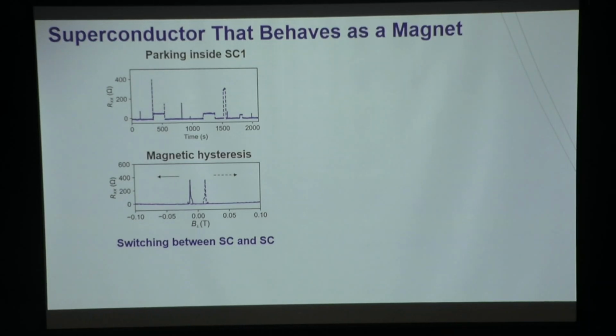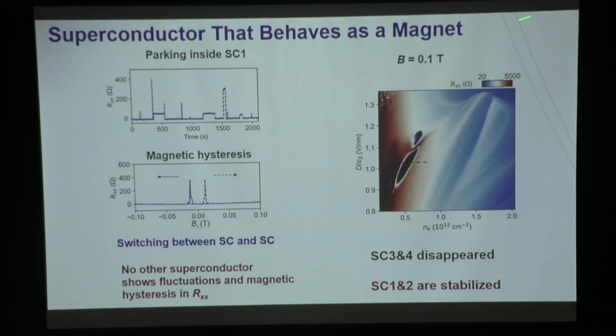Okay, let me pause a second here. We all know superconductors do not like magnets. If you're in a bulk superconductor, you have the so-called Meissner effect, where the magnetic flux will be expelled by the superconductor. Well, when you go to two dimension, the magnetic flux can penetrate through the 2D layers, right? That's fine. But we're talking about the superconductor not only can get along with magnetic field, but itself behaves as a magnet. Because a magnet will fluctuate from pointing upward to downward. A magnet will have hysteresis in response to a scanning magnetic field. So we are talking about a very bizarre superconductor that behaves as a magnet.